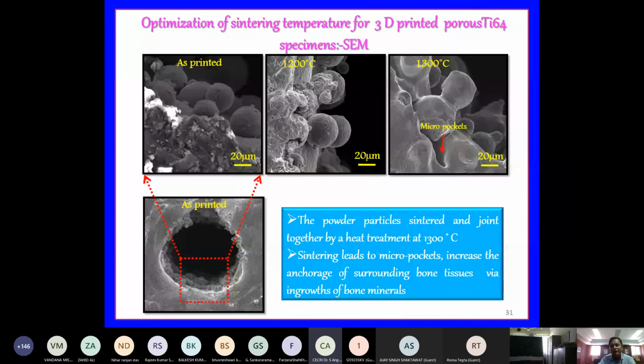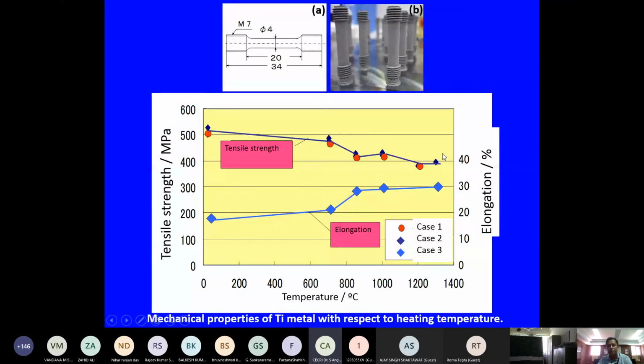Here you can see another slide where, interestingly, because of the heat treatment, we can bond these loosely bonded particles inside the pores, and because of this, it can form the micro pocket. This type of micro pocket is very much essential for biomedical application, because the tissue integration will be more firm and more strong. And we do a lot of mechanical properties evaluation.